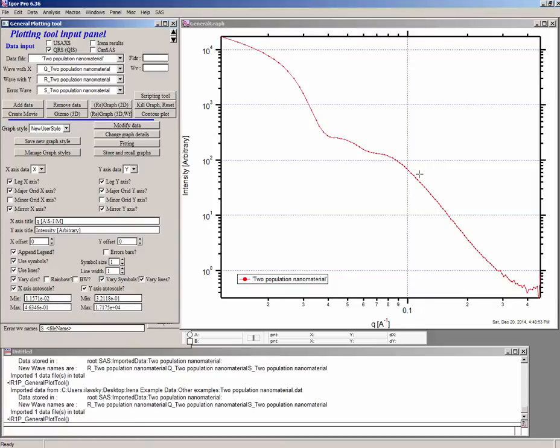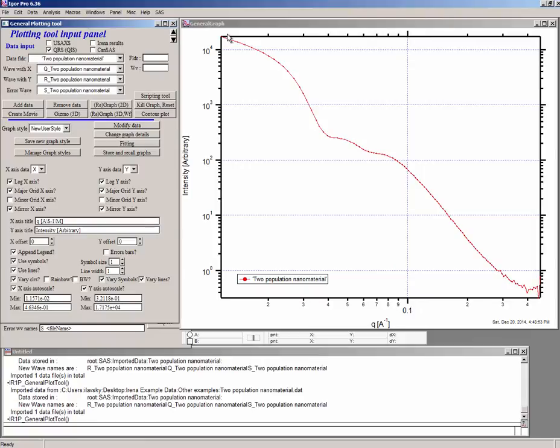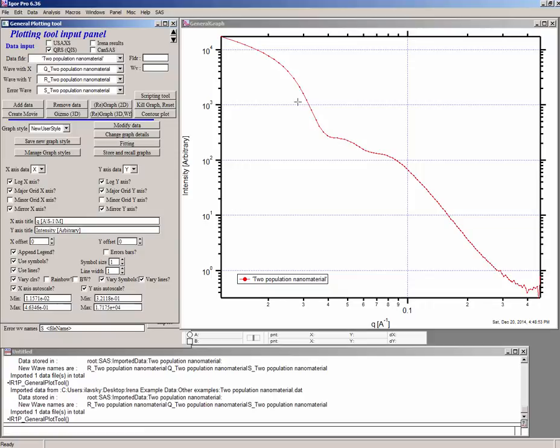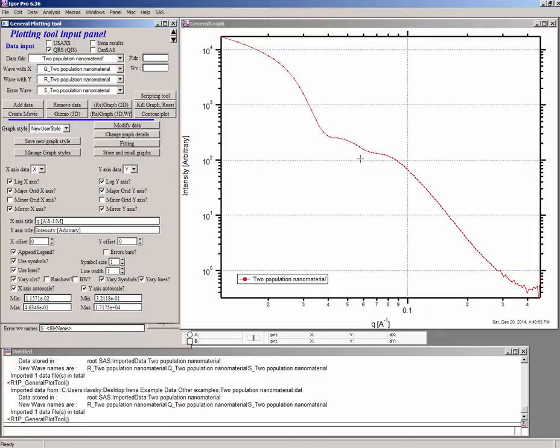The other thing we need to think about is how are we going to fit this data set. Now I'm telling you this is two population nanomaterials. These were two nanomaterials mixed together. The first thing which you can look at there is there is obviously a Guinier area and there's a kind of secondary hump to it. If the larger material is sufficiently monodispersed, it would possibly produce these Bessel function oscillations. And with a little bit of training and an eye, I can actually tell you this is a second order oscillation of this one. But the IRENA code will actually tell us this thing. So we will find out.